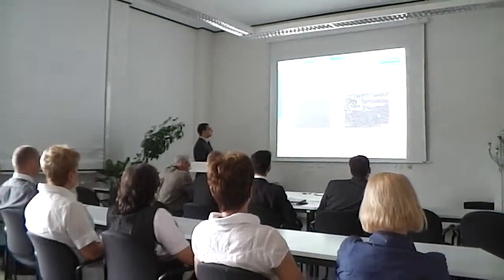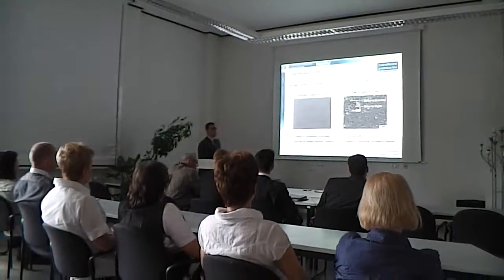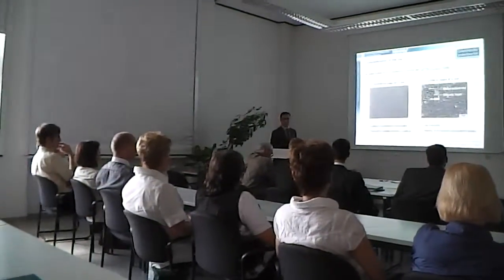Different concentrations of the sol were tested. 6%, which is prepared from this ratio, GPTMS, TEOS, and water. The scanning electron microscope for the surface of this film showed that this film does not completely cover the surface. Here is the metal, aluminum, and here is the silica layer. So therefore, the samples coated with this film have no corrosion protection, no barrier property, and no stability in chloride solution.